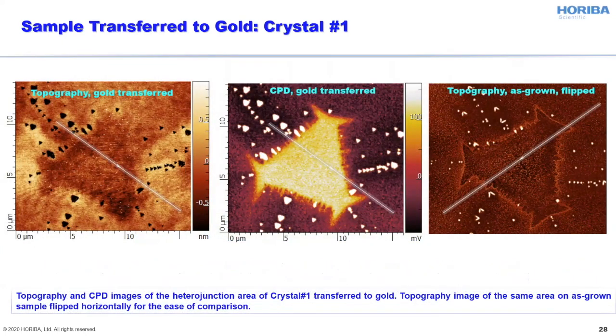So topography expectedly was very smooth, because realistically we were looking at the replica of an extremely well polished silicon wafer, and the contact potential difference from Kelvin probe microscopy was showing very nicely the presence of this core-shell structure, molybdenum disulfide core and tungsten disulfide shell. And to compare it with the original topography image, to confirm once again that we are dealing with the same crystal, you can see the right image here. That's the flipped topography image of the original crystal on the growth wafer.